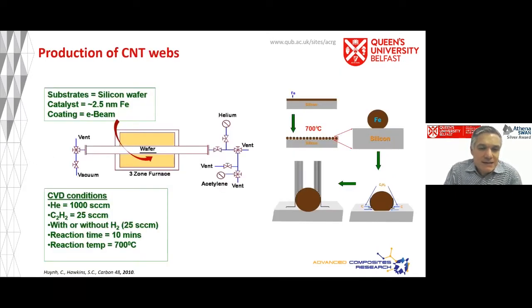So the way we make it is that we have a quartz tube here. We have a silicon wafer with a catalyst, which is usually iron, and that's a very, very fine catalyst layer that we put on that silicon wafer, usually with an electron beam, but you can use lower types of technologies like a sputter coater. And then when you heat this up, you get a fragmentation of that catalyst, and they serve as initiation sites for growing your carbon nanotube vertically.